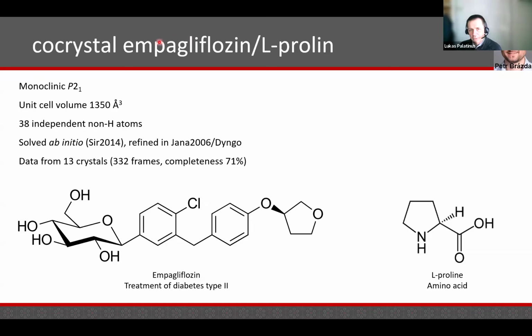This is a co-crystal of empagliflozin and proline. And the question here was to test or confirm that this co-crystal is indeed a co-crystal and not a salt. If it was a salt, that would mean that one of the hydrogens of one molecule would shift to the second molecule, making one molecule negatively charged and the other positively. So our task was to exclude this possibility. So what we did, of course, was to remove the hydrogens that might possibly be cleaved away and moved to the other molecule, and see if we can see the positions of the hydrogens in the difference Fourier map.